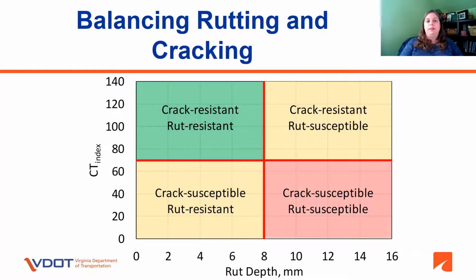The purpose of BMD is to balance rutting and cracking susceptibility of a mixture. The idea is that we want to minimize the rutting and increase cracking resistance. We're going to be looking for a rut depth in testing less than 8 millimeters and a cracking index, CT index, greater than 70. You can see this in the green shaded box. These mixes should be crack resistant and rut resistant.